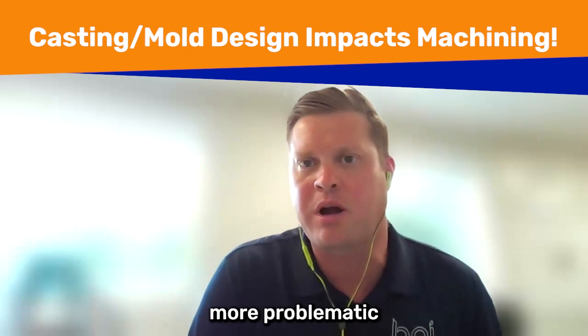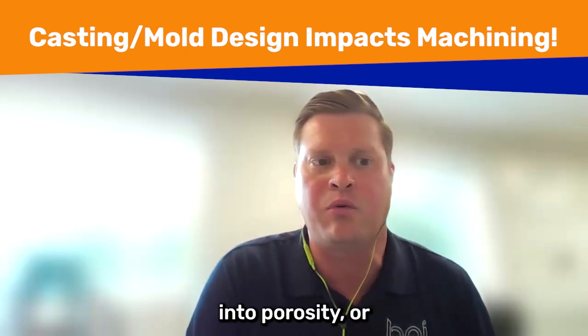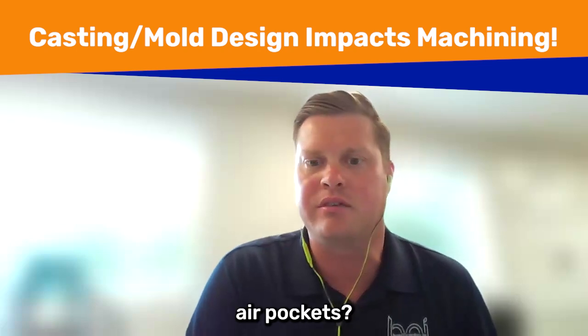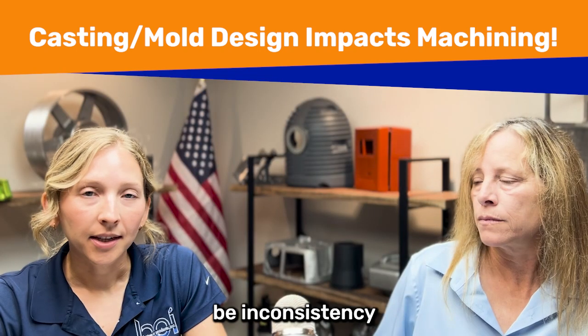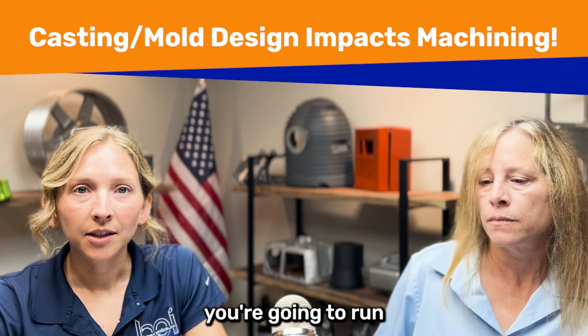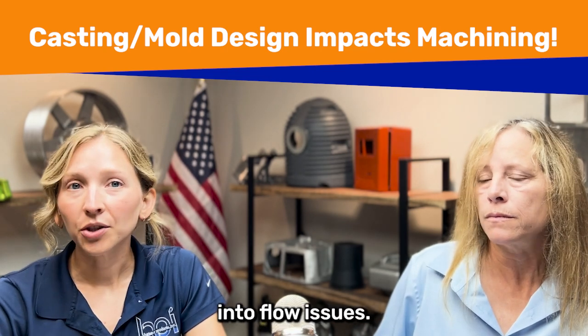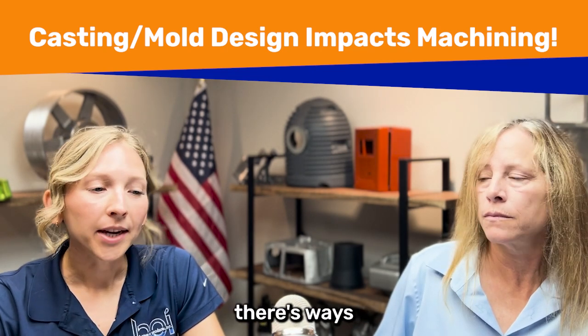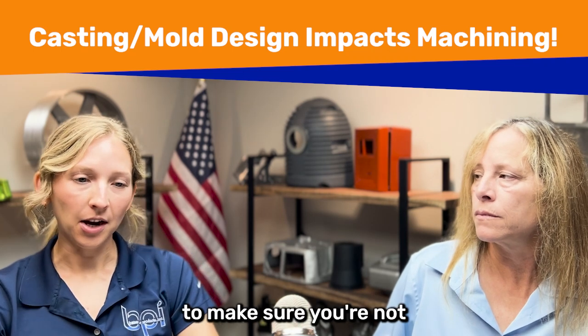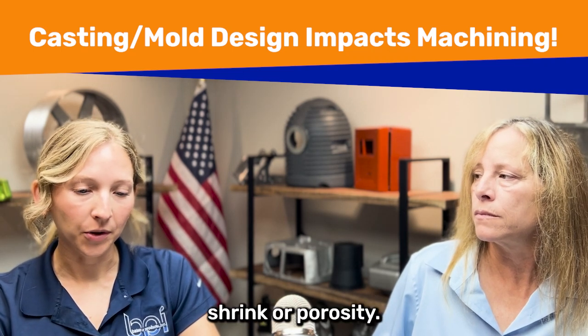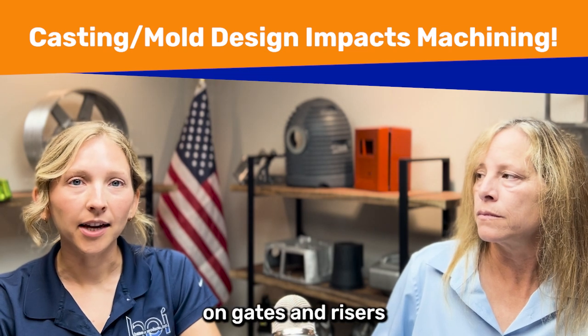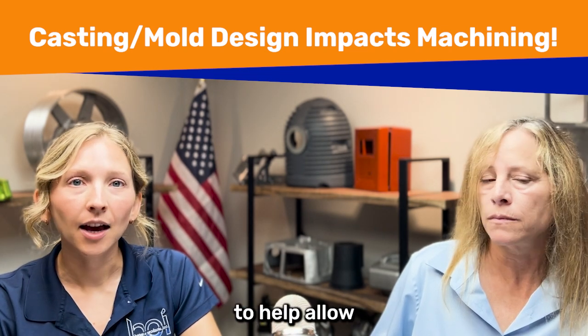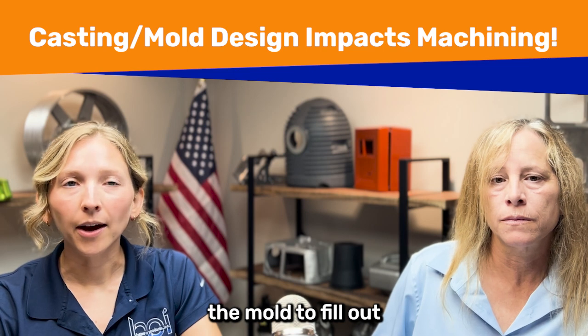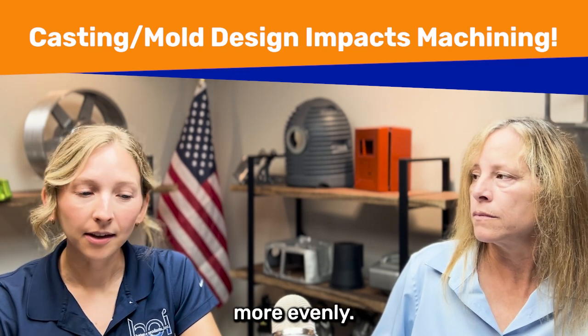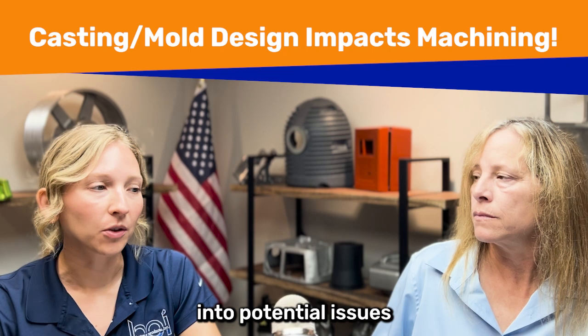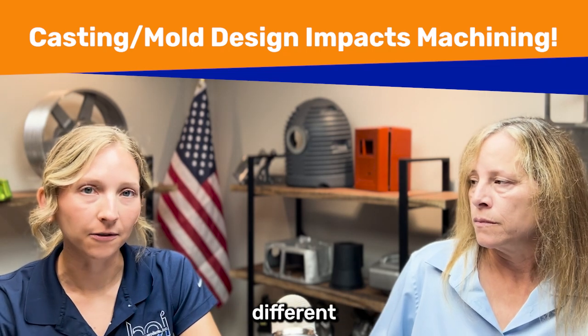Can it become a little more problematic if you run into porosity or potential air pockets? If there's going to be inconsistency in wall thickness, you're going to run into flow issues. So there's ways to work around it to make sure you're not getting any shrink or porosity. So we can add on gates and risers and venting to help allow the mold to fill out more evenly, but you will run into potential issues with that if you are requiring different wall thicknesses.